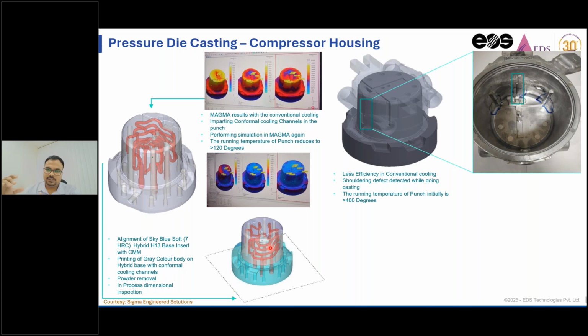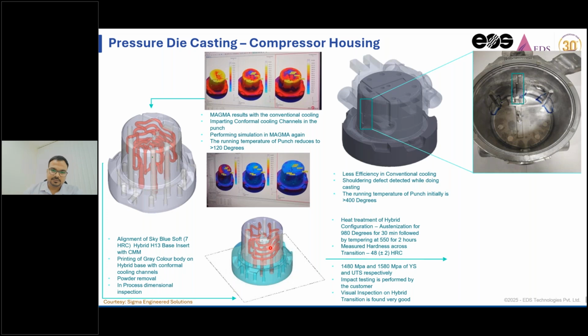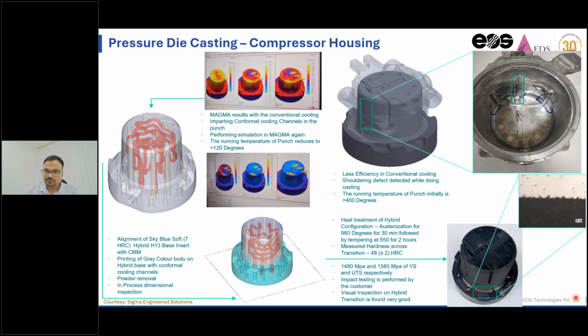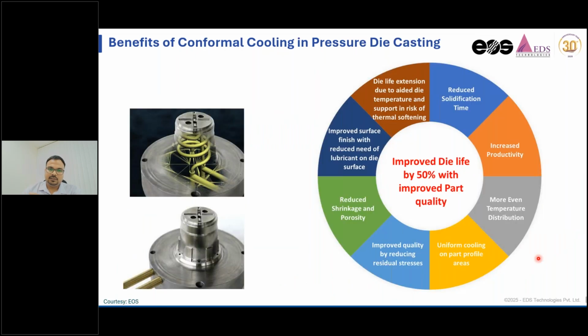So we only have to print the portion of the mold or the portion of the tool that has the geometrical criticality. You don't have to print the entire mold or entire component or entire tool altogether, and the process well supports it. So we printed the complicated portion and calibrated the hardness across the mold, and it performed well. The joints were completely fine, and they were giving high strength at the transition also where we joined it, and the problem was solved basically. So conformal cooling is able to reduce the rejection and improve the performance of the overall molding process.